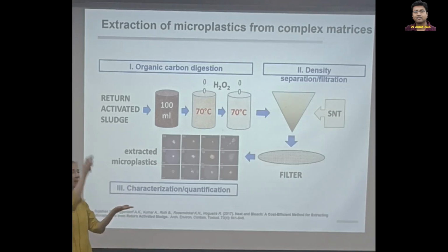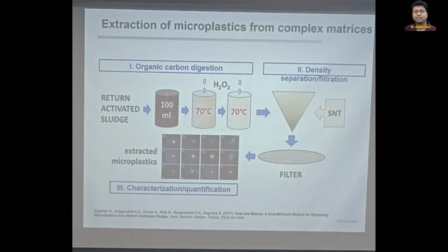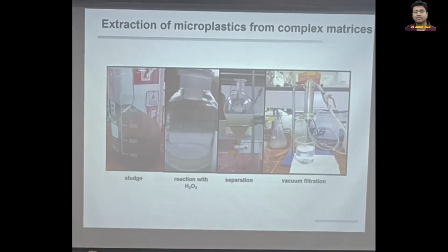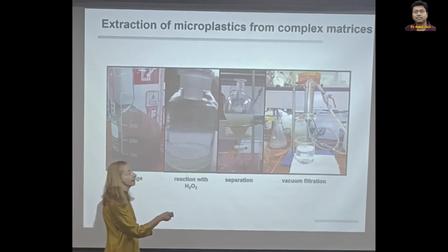The plastics are already in the filter. If they are in the filter, then in this case, we went for Raman spectroscopy to identify the type of polymer. Okay? This density separation, here is only a photo of the lab procedure. You have here the sludge, and you see after the sludge is this dark brown. After digestion with hydrogen peroxide, the color is much lighter because the organic matter was digested. Then I have to separate the plastics, and afterwards I have to put the plastics on top of the filter, and I need a filtration unit.